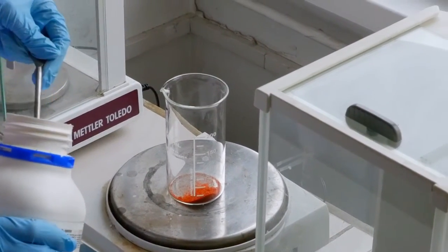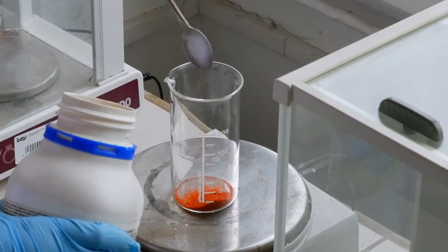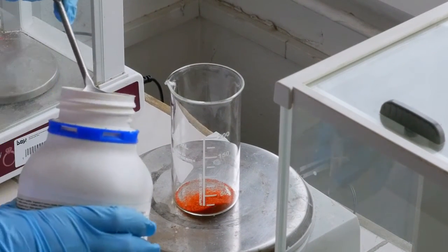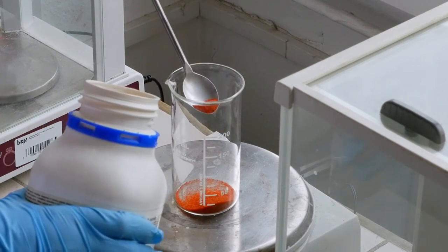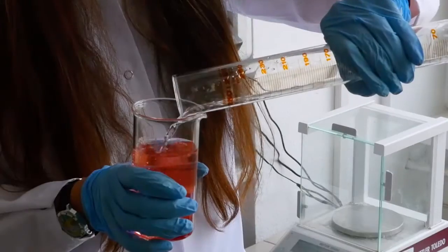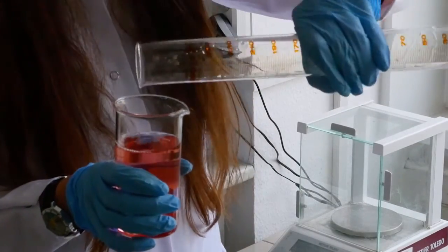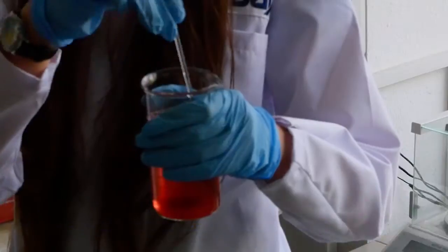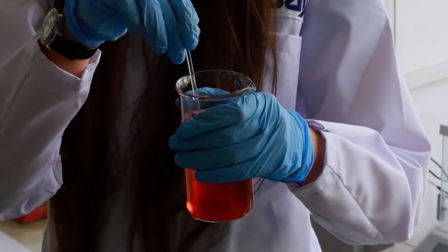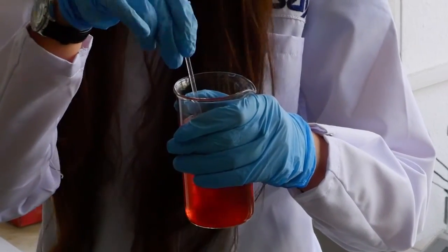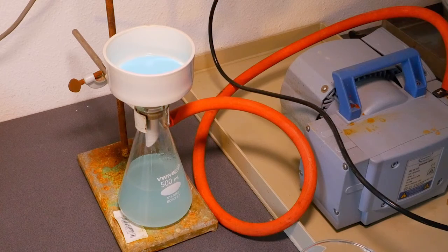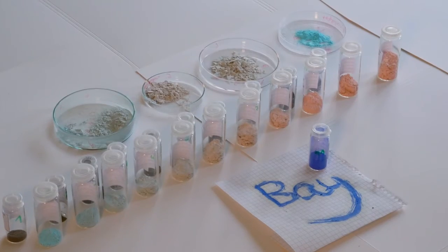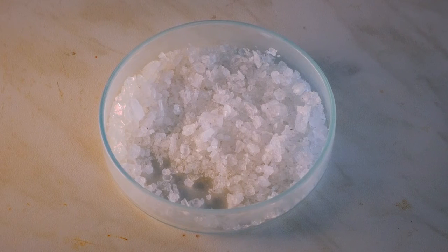to reutilize the electrolyte. The electrolyte is mixed with a solution of transition metal salts, typically copper and cobalt compounds. After mixing, precipitation occurs, and depending on the composition of the solutions, the color of the precipitate will vary. After filtration, the solid material can be recovered and used as a pigment. This is how our work and role in the RADIUS project looks like.